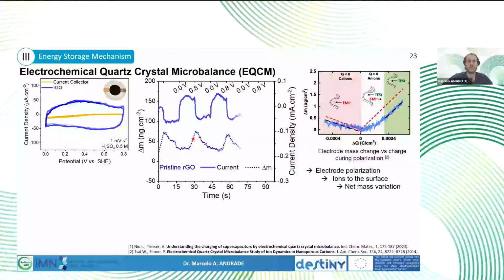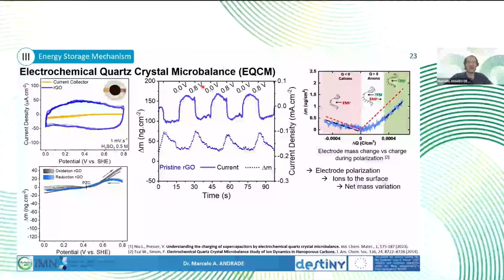And what we saw was exactly that. So that's the mass variation of the RGO with the current. Once we had a positive polarization, we had an increase in mass, and then with no polarization, we have a mass decrease, and that was reversible. So these are the same plot with different axes. We see a very pronounced mass increase in positive, and then a less pronounced mass increase since we are in sulfuric acid and we have protons as a cation. There's another animation that is showing the polarization and the anions that arrive to the surface, and here the protons or hydronium cations that come to the surface when we polarize it negatively.